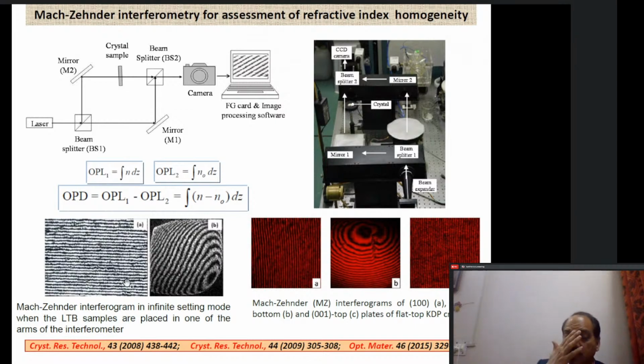This is for the lithium tetraborate sample, and you will see that these straight and parallel lines show that the crystal is free of major defects. And here you will see that although the fringes are parallel and straight, they are not equispaced. This is because there is a curvature in the sample after polishing, so that curvature is showing these types of artifacts in the fringes.